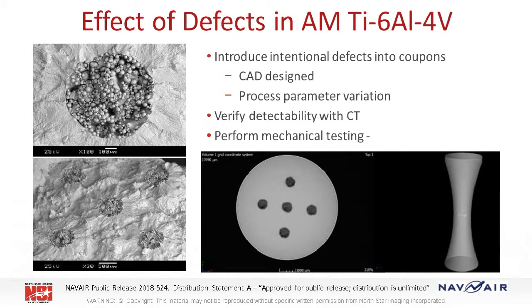Here's a great set of images from NavAir where they designed and printed a specific size and orientation of unfused powder defects into coupons. They then verified the detectability of the defects with CT prior to performing mechanical testing. And obviously, this data can be really useful in FE models.